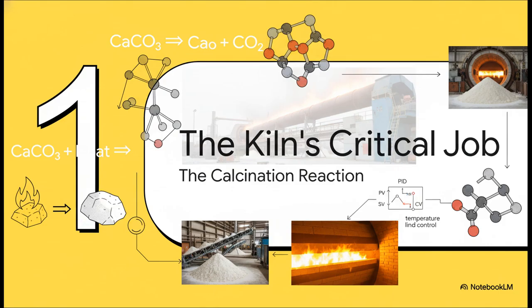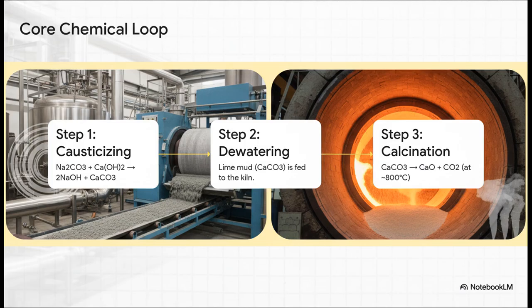We have to start with the calcination reaction because this is the fundamental chemistry that makes the entire recovery loop work. So it all begins back in the causticizer. That's where we make our cooking liquor. And in the process, we precipitate out calcium carbonate, CaCO3. That's our lime mud. We dewater it, then we feed it into the kiln.